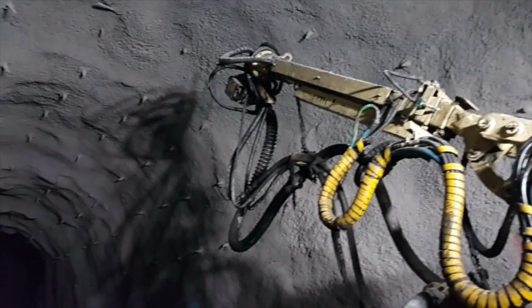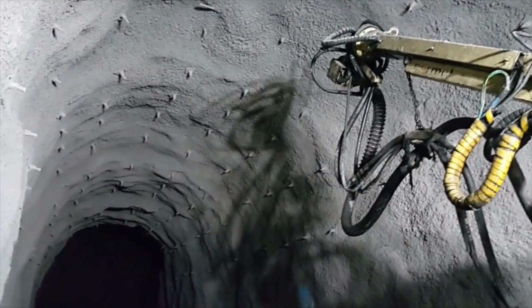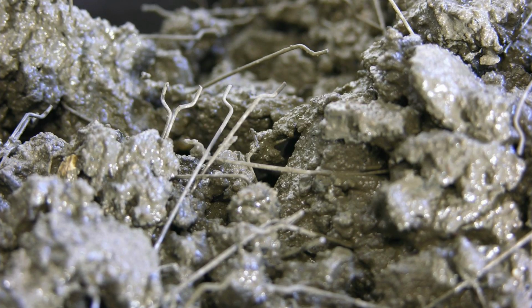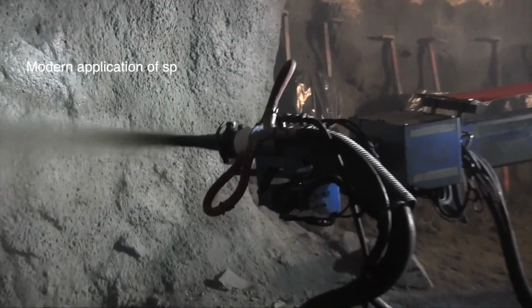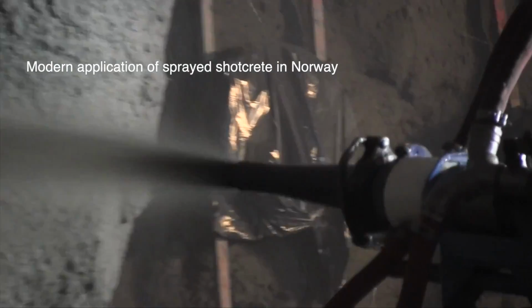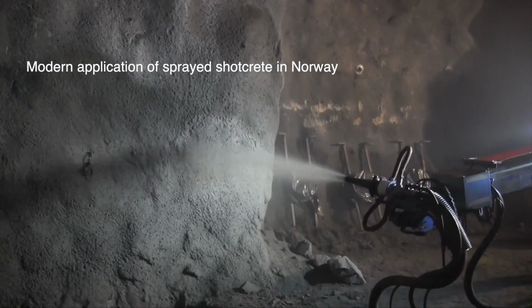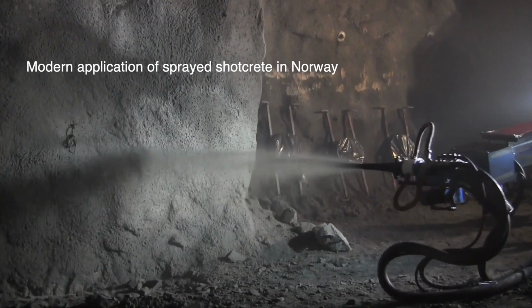Once you see that the deformations get stabilized, then you know that the strength is okay. You also have to avoid that your concrete is just too strong, otherwise it will become brittle. To avoid this brittleness, you have to add more fibers, or fibers of a higher quality. And that's what's going on today. Norway has a good quality rock. That means that a shotcrete layer is enough to stabilize the underground. And there, they were using steel fibers already at the end of the 70s, early 80s.